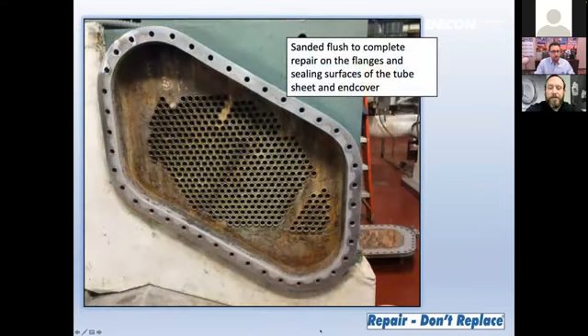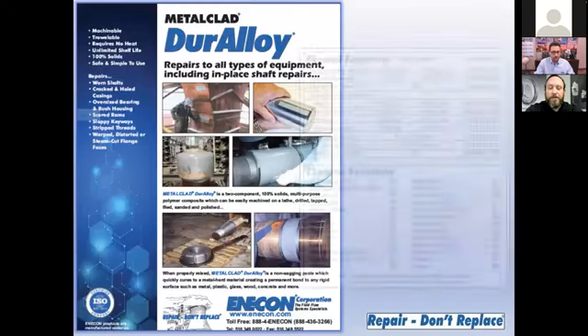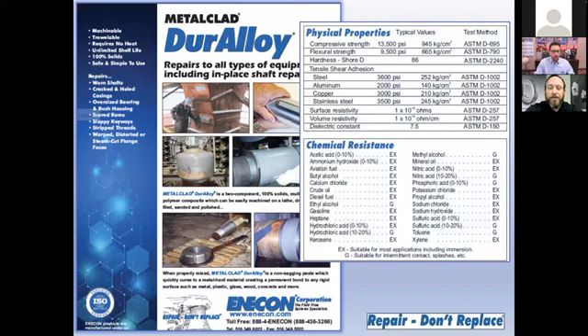Once the Duralloy has cured, we sand the Duralloy back down, making sure that it's flush all the way around the flanges on the tube sheets and end covers. And the next day, it's put back in service. Duralloy is the material of choice in this application because it has a very quick cure as compared to the ceramaloid paste. Duralloy is ENECON's quick curing machinable metal repair material that exhibits outstanding compressive strength and adhesion and is the perfect product for rebuilding flange areas and other types of metal surfaces as well.